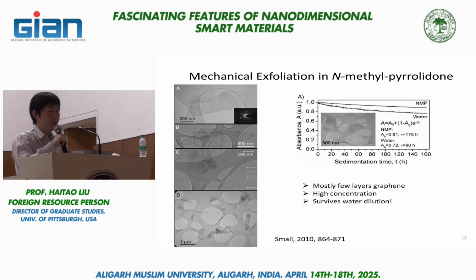What is more interesting is even though this exfoliation is done in an organic solvent, now NMP is organic and is toxic, and people don't want to use organic solvents, they want to use aqueous systems. What they found is that after the exfoliation, they can dilute the organic suspension with water by 100 times. So now you turn the organic suspension into an aqueous suspension. So the organic to water ratio is 1 to 100. Even in that condition, the suspension is very stable. You look at this second curve here. The curve behind the NMP shows a little bit more precipitation, but over 160 hours, only 20% of them precipitate out, 80% still remains.